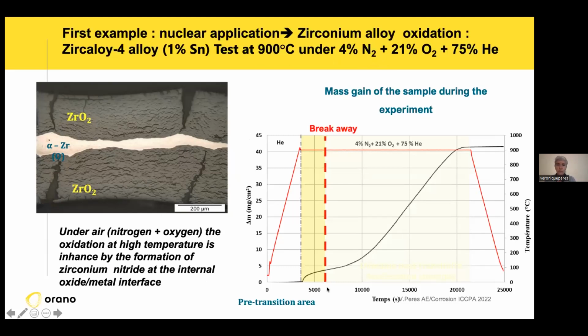In this graph, you can see the mass gain of the sample during the experiment. In red, you have the temperature curve, and in black, you have the oxidation. At the beginning, you have a very normal oxidation behavior, which is a parabolic one, but after a transition, a breakaway, you have a quick increase of the mass gain. So it's very critical.